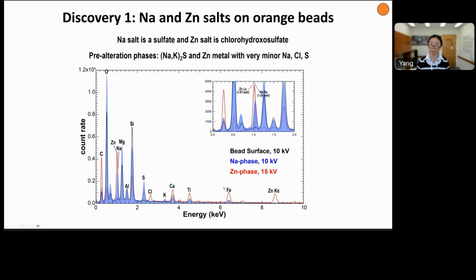With a constrained chemistry, we can infer that the zinc phase, the red curve in this plot, contains high zinc, high chlorine, also high sulfur, as well as some sodium. The sodium phase, the blue filled curve, contains only sodium, potassium, and sulfur, no chlorine. So we use the elemental chemistry to infer the precursor phases. The reason is that the Apollo 17 orange beads were collected on the moon but not sealed in vacuum. Those samples were stored in the airlock on the lunar module that experienced depressurizing and repressurizing cycles, so the samples have seen the cabin air on the lunar surface.